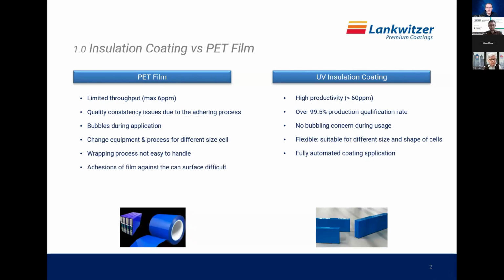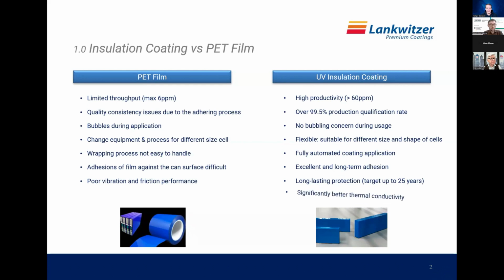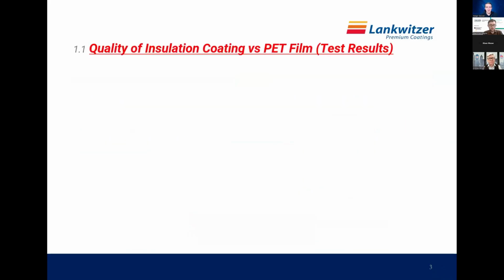The adhesion of the film against the can surface is normally very low on PET film. It's very high on UV insulation coating. We're going to look at this in the next slide. Poor vibration and friction performance, that's super important for cars. It's important for trucks on challenging roads in various parts of the world. Long-lasting protection. So the target for us now is up to 25 years. And significantly better thermal conductivity. So that's a rough overview. PET film to the left, UV insulation coatings to the right.